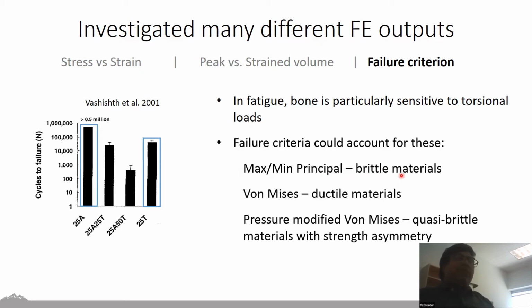And this is a criteria that has worked really well in the past for brittle materials. The way this works is you look at the deforming material and you try to find the direction in which it stretches the most or stretches the most negative. Those are the max and minimum principal strains. Another criteria that we looked at was the von Mises criteria, which is something that works quite well for ductile materials, but has also seen a lot of use in bone. This criteria basically separates out the deformation into a hydrostatic or volume changing component and a deviatoric or shape changing component. And it says that failure is based on the energy associated with the shape changing component of the deformation.